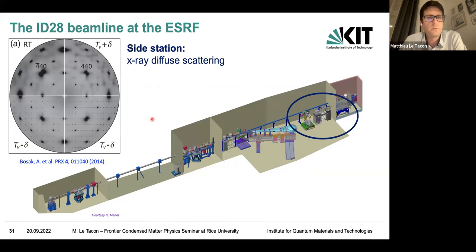Before that, we made use of a very nice option of the ID28 beamline, the X-ray scattering beamline, which has a thermal diffuse X-ray scattering station next to it. Basically, what you measure here is a diffraction experiment where you mostly saturate your Bragg reflection, and you can look at the diffuse scattering between the Bragg peaks, and that happens to be extremely useful to find your way in reciprocal space.